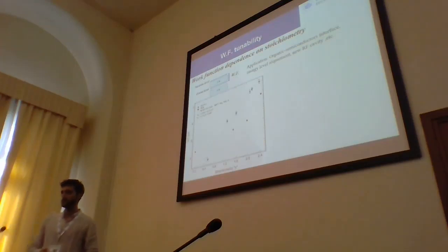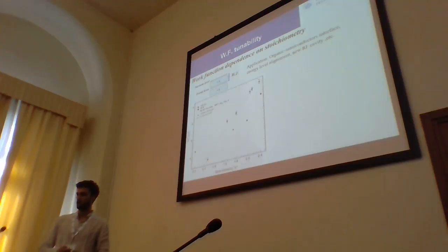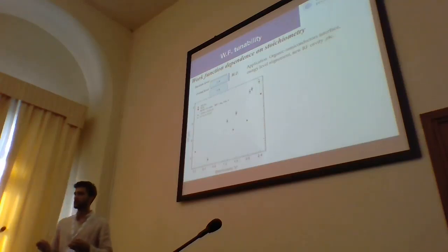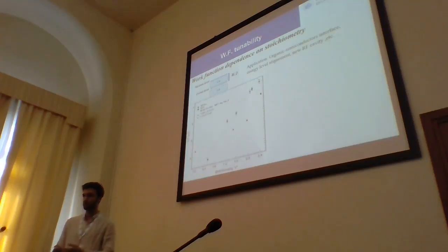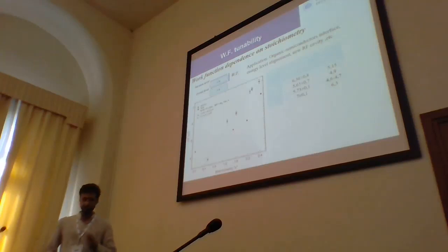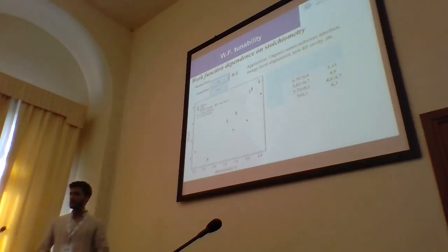Then, very quickly, I show you also that by tuning the oxidation state, we are also able to tune the work function as a function of stoichiometry. The work function is the energy which separates the Fermi level from the vacuum level. This is a very important parameter in all the applications which involve charge injection at interfaces, since basically by tuning the work function, you can tune the Fermi level. And we see from this graph that our experimental points, which are the black dots, are systematically higher with respect to the bulk analogs, which I took from literature.